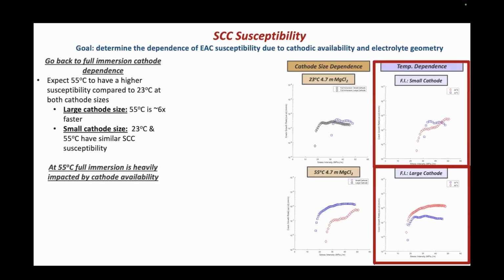If we go back to that full immersion cathode work that we talked about, where we just painted the samples, we could see that at that large cathode availability, 55C, which is this red one, because I don't think you can see it, 55C is this red, the blue is 23C, and same for these. At the full immersion large cathode, the 55C is about 6 times more susceptible, or faster in crack growth rate, than the 23C. But if we limited both of their cathode sizes for the small cathode, they're pretty similar, and you would expect 55C to be more susceptible than 23C.